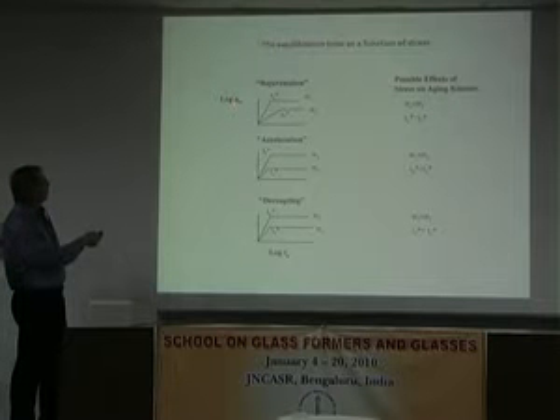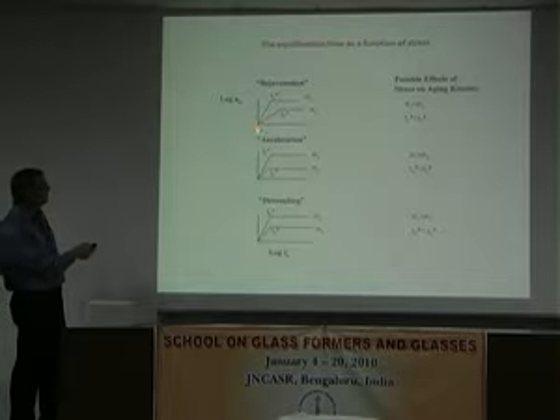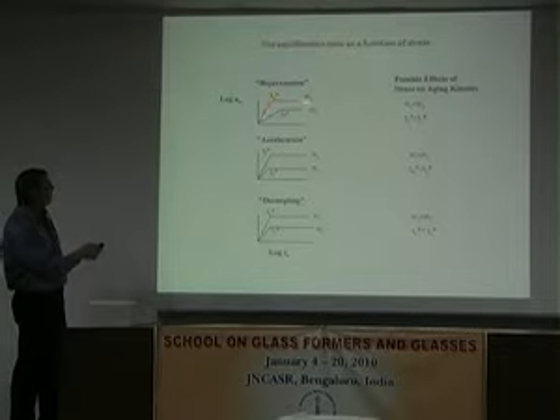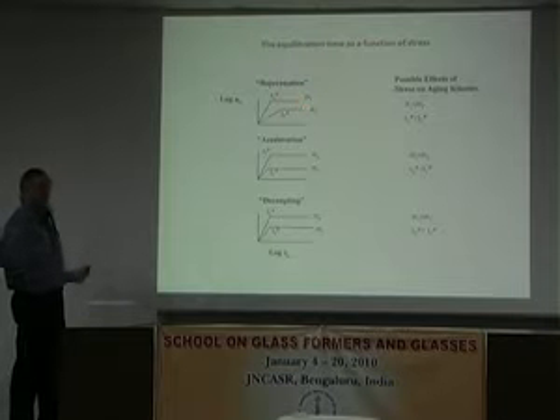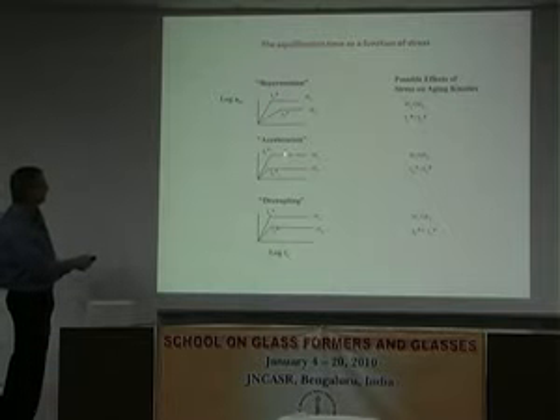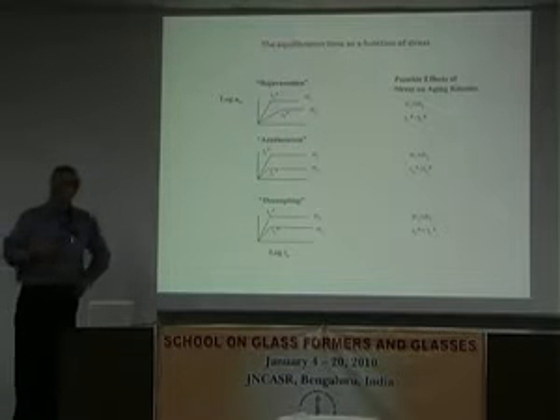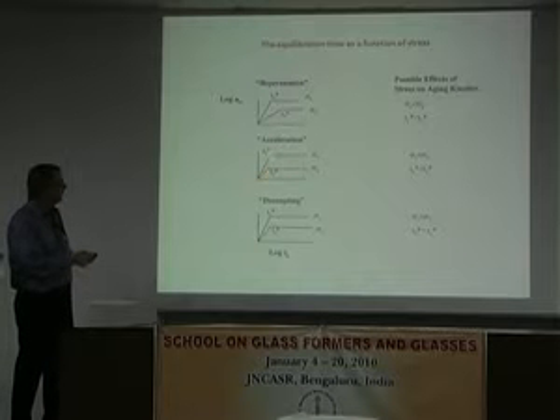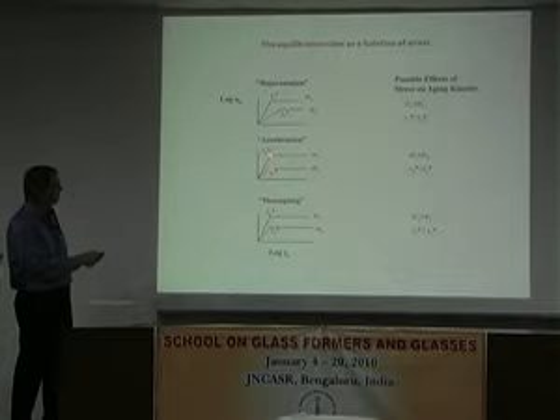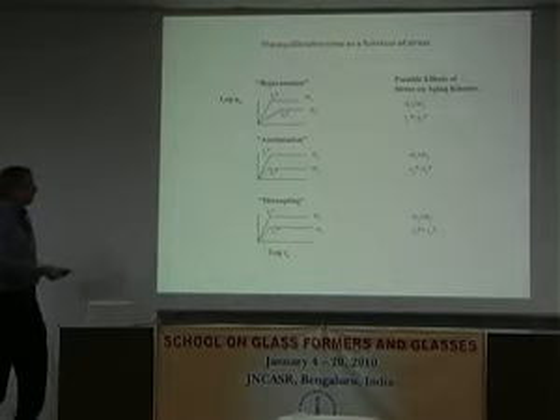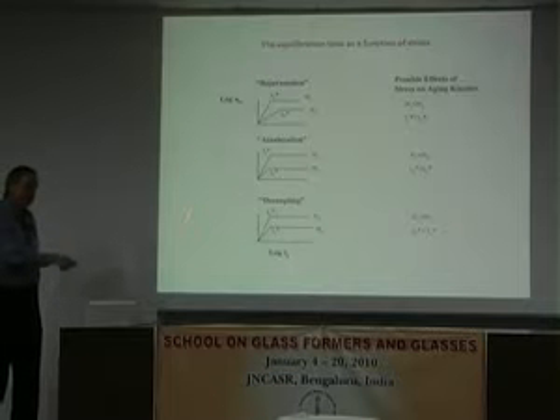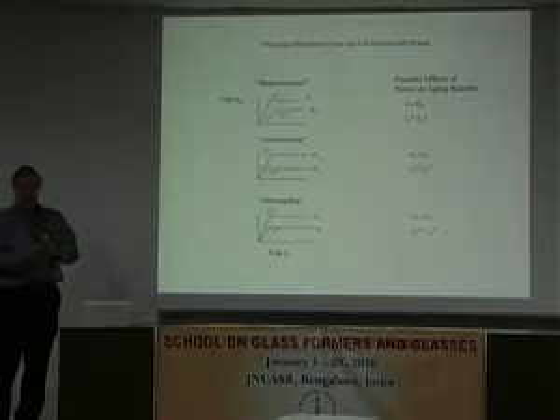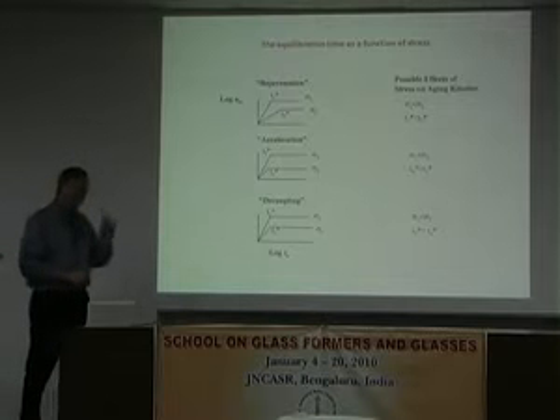But here was the idea: if you really had this rejuvenation, at least the signature of it would be that if I age it into equilibrium, and this is a schematic, and we never get that, but if we go to a higher stress, it's going to go to a lower place, and it's going to take longer because I've rejuvenated it. The other possibility is that at that time, there was somebody at RPI, Sandy Sternstein, who was arguing, in spite of that lower shift rate, that I'm actually accelerating the aging, in which case T star 2 would be smaller than T star 1. So we had to test that hypothesis too. And then, of course, the possibility that you're not really rejuvenating the glass, and your mechanical stimulus is not directly impacting the underlying structure of the glass. And so we want to look at this question.